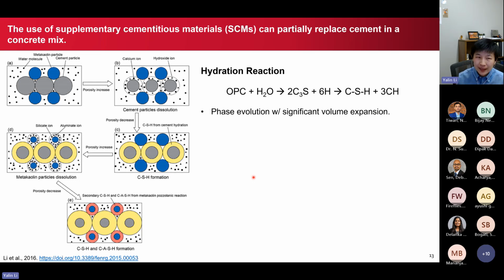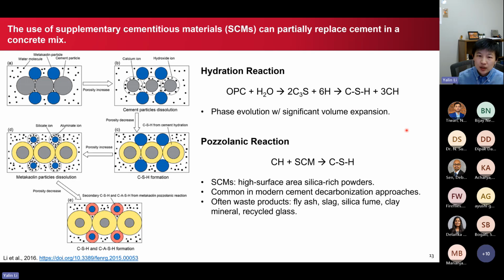When we are thinking of how we can reduce the amount of emissions in concrete, the first low-hanging fruit is to use some supplementary cementitious materials, or SCMs, to partially replace cement. Recall that cement is essentially the binder material in this concrete. When you harden the concrete, there are hydration reactions that turn the OPC into calcium silicate hydrates, which are the active materials that can bind the aggregate together. Some SCMs can also form these binding calcium silicate hydrates, so they can be used to partially replace the cement and therefore reduce the total emissions.